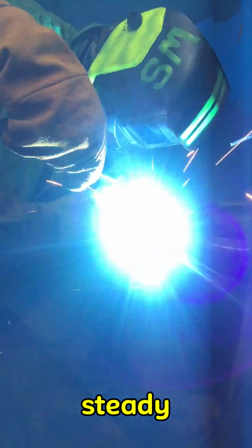To wrap it up, position your joint at 45 degrees, clean off all mill scale, split your work angle dead center, keep a steady travel speed, and clean between passes. Do these 5 things, and your 1F fillet welds will be flawless.